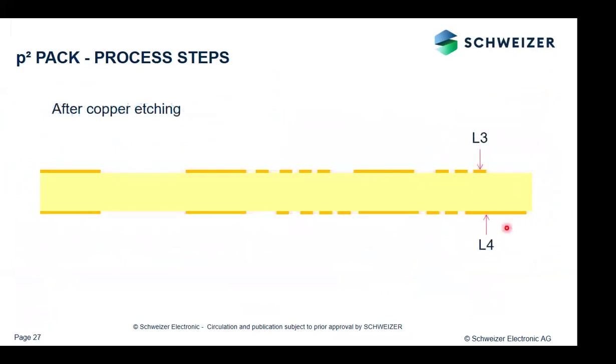And in the first step, you're making a print and etch, a photolithography process with a photoresist, imaging, developing, etching, and then you create a pattern like you want to have it. And as we are making a 6-layer construction, this will be the layer 3 and this will be the layer 4. And after copper etching, you have your pattern. And here you have a special area which is released from any copper, because after the manufacturing of this inner layer, we are creating an opening in this layer with a milling process.